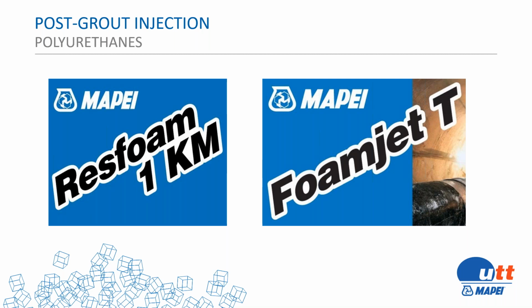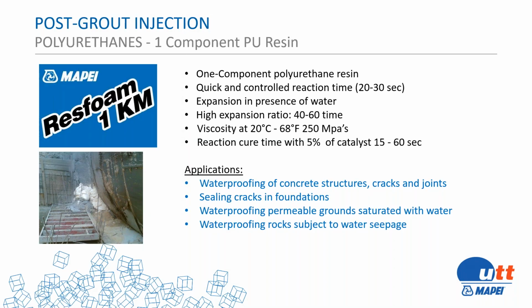So we have the Resfoam family and the FoamJet family. In Resfoam, we have Resfoam 1KM, and this is a one component urethane. It's hydrophobic, it's quite a fast reaction, and it has a tight cell structure. We use it quite a bit because it's easier for mobility in terms of using an airless spray pump. We also have within MAPEI the other Resfoams, which are the 45, which is hydrophobic, the 35, which is hydrophilic, and our SS75. They are all NSF approved. So many times underground where we have the requirements for NSF material, we have the viability of using those. We use this one component urethane quite a bit, and it's also made right here in America. Next slide.